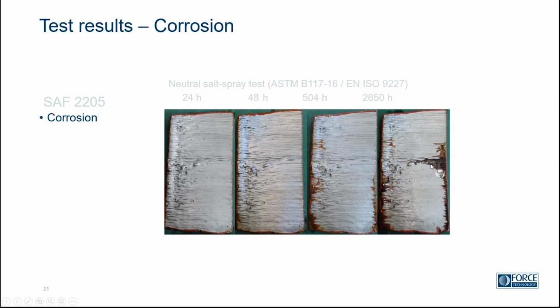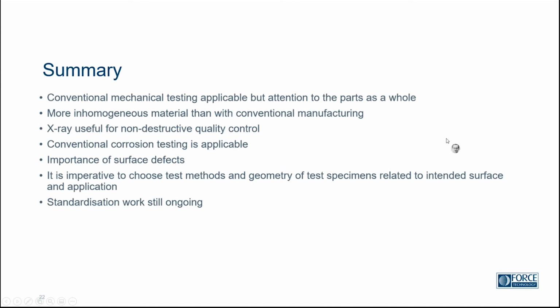When you clean this panel, you might be inclined to say, okay, this is not good enough. That's not true. When you clean this and look at it, there's actually no damage on the panel surface itself. What we have is a slight crevice forming under the protective paint along the edge, and that runs with the corrosion products out on the surface, because we have a sort of wavy geometry on this, although it is a plate. So, to summarize it very shortly,